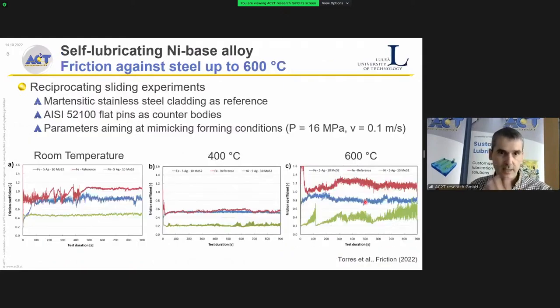So we check this nickel self-lubricating alloy under different conditions. The first one is, for example, reciprocating sliding model experiments against martensitic stainless steel. We always use some material as a reference. In this case, we also use martensitic stainless steel cladding as a reference, this is the red line.